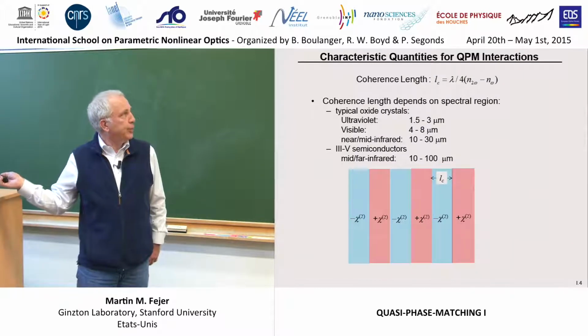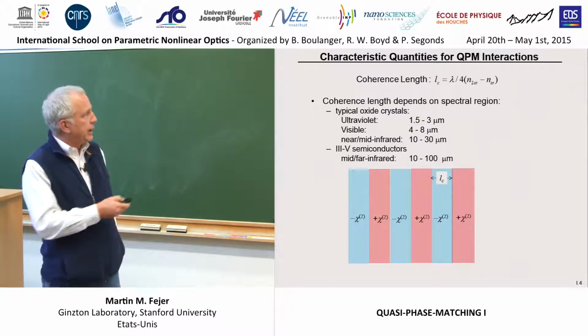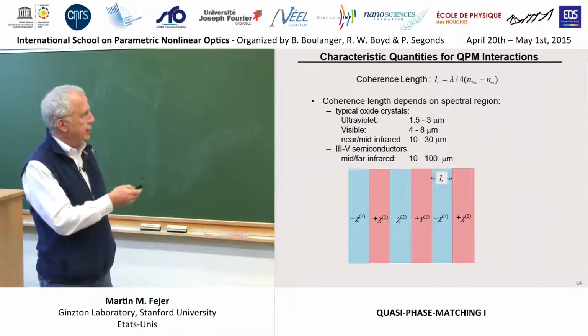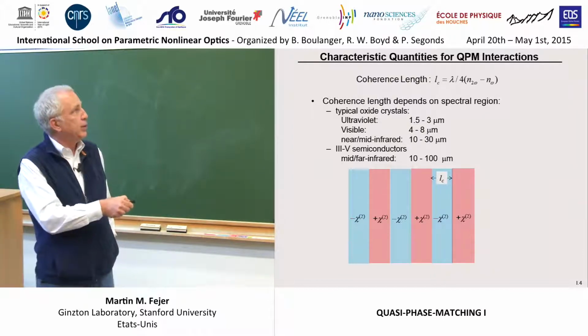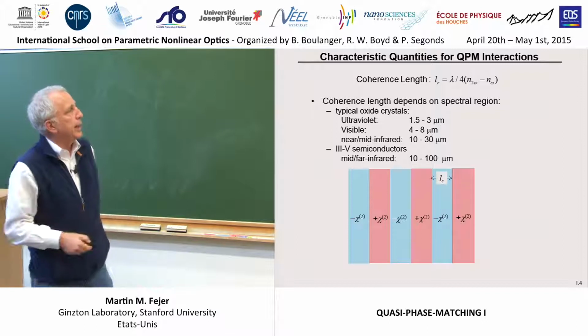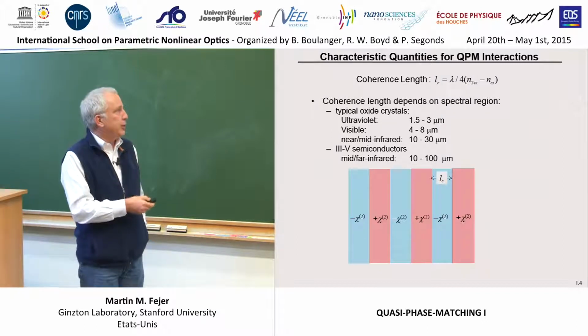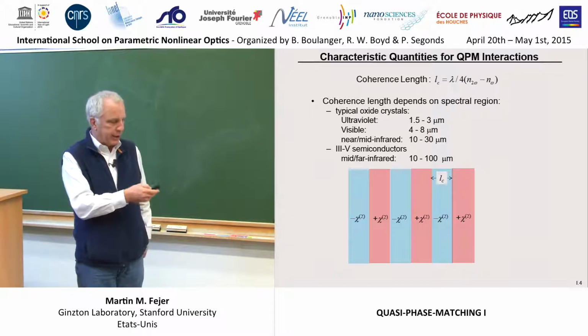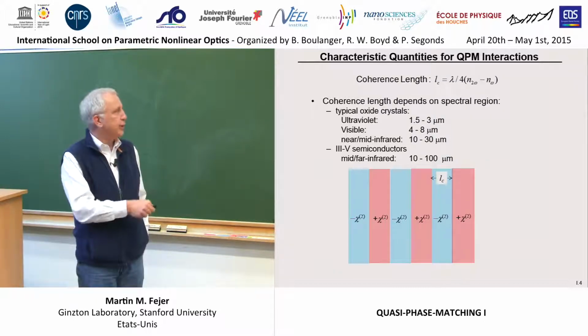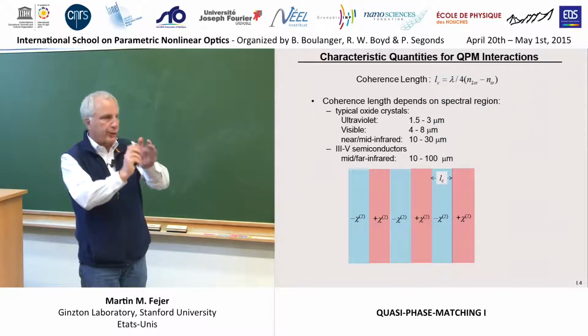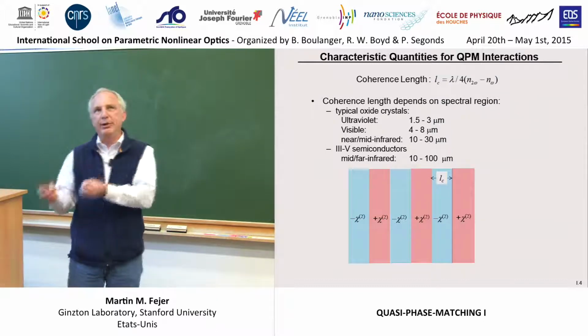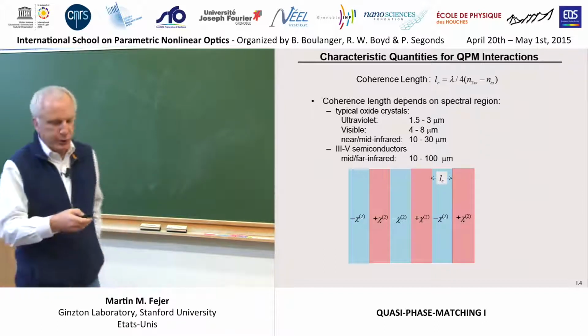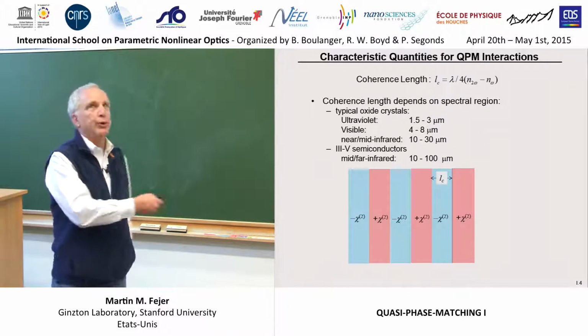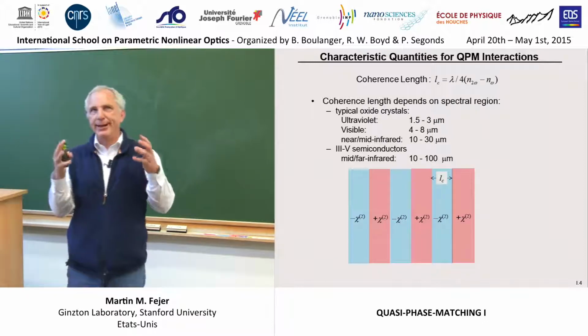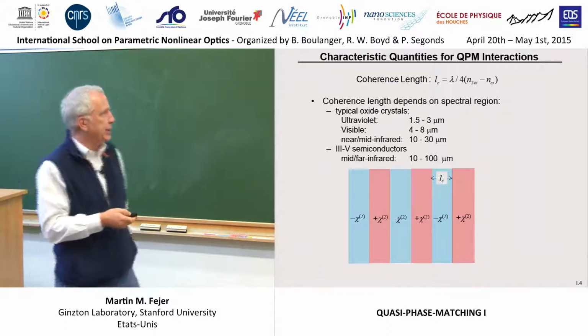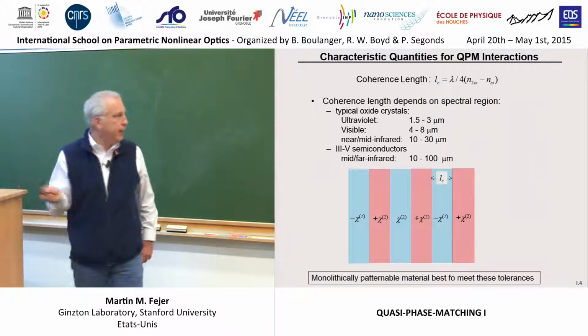That's not an easy thing to build. In fact, if you're working into the visible or near UV, you're often talking about just a few micron layers here, and even in the mid-infrared, only a few tens to maybe 100 microns. And so rather than stacking up a collection of plates rotated 180 degrees to make such a structure, one really needs a monolithic technology, ideally under lithographic control, in order to keep the long-range order in such a structure, as well as to have some mechanically plausible piece of material when you're all done.